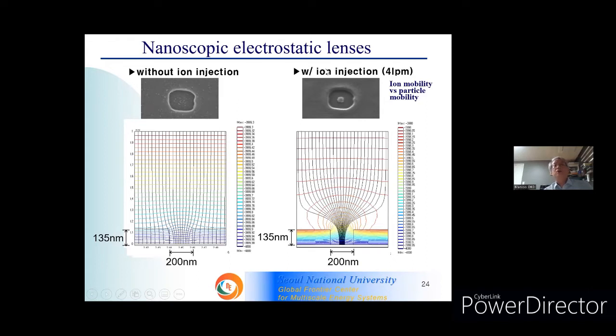But we inject ion, so ion accumulation on this photoresist layer will modify almost flat equipotential plane into convex shaped equipotential plane. Electric field should be in a direction perpendicular to the equipotential plane, and then charged aerosols should follow this electric field line and deposit only at the center of the opening area.